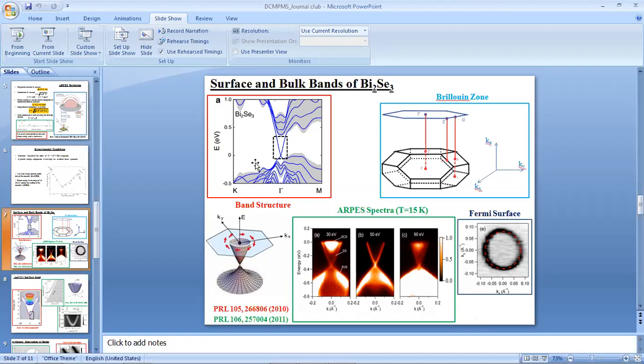Yeah. Now, this zero scale here is not actually correct. This is theoretically predicted. The prediction says that the Fermi level should go across this Dirac node, this cone. But actually this sample is electron doped. That's why the Fermi level is here, where you can see some of the bulk bands also. So this theoretical prediction is not correct. If you want to directly match it with the experiment, this zero energy has to be shifted to here.